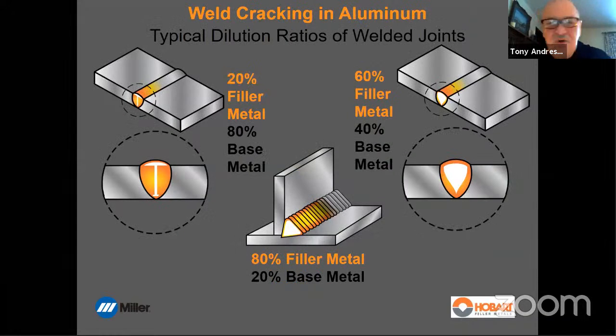So what does this mean in reality? People call me sometimes and say, hey, I'm welding 6061 groove weld with 5356, and it keeps cracking. I ask, what joint preparation? Well, I'm using a square edge joint prep. I say, put a V prep on there and see what happens. If we have a square edge prep, we're looking at about 20% filler metal and 80% base material. That weld is going to be a composition of 20% filler, 80% base.